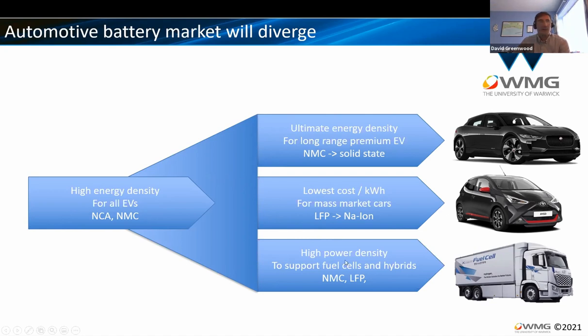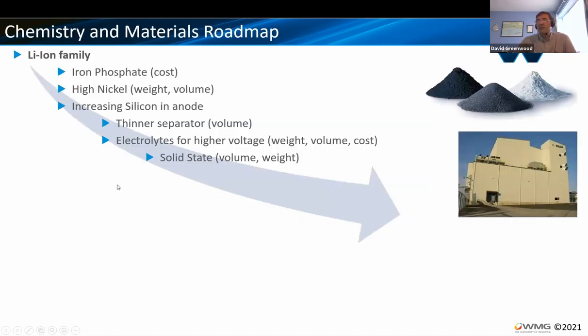And then in smaller volumes, you'll see this need for high power density to support fuel cells and hybrid type vehicles. So what that means in terms of the roadmap is that the lithium ion family of chemistries is going to be around with us for quite some time in a couple of different forms. So things like the iron phosphate chemistries, which focus on low cost, the high nickel chemistries that focus on high range, and you're going to start seeing increasing quantities of silicon being used in the anode in order to improve the energy density of the anode part of the battery.